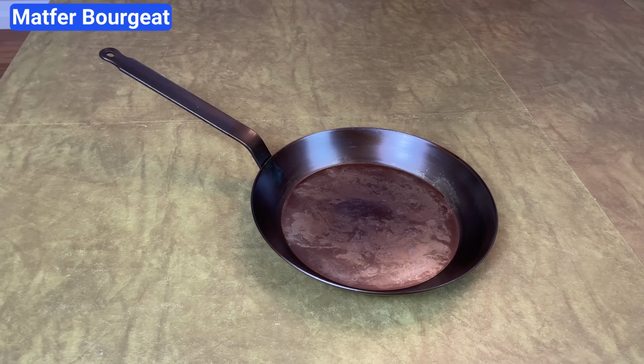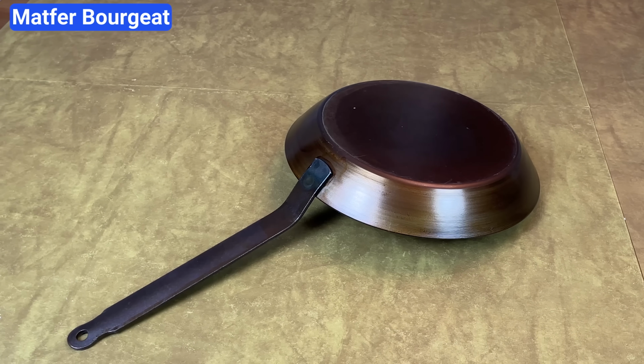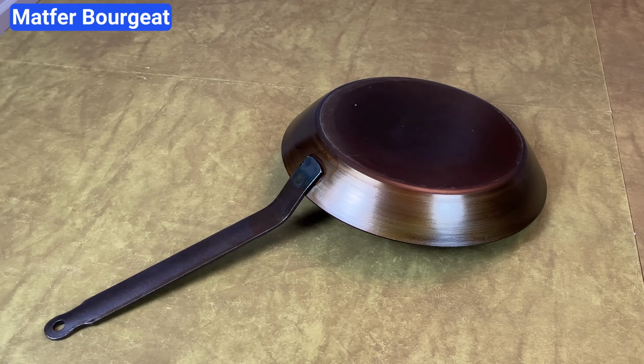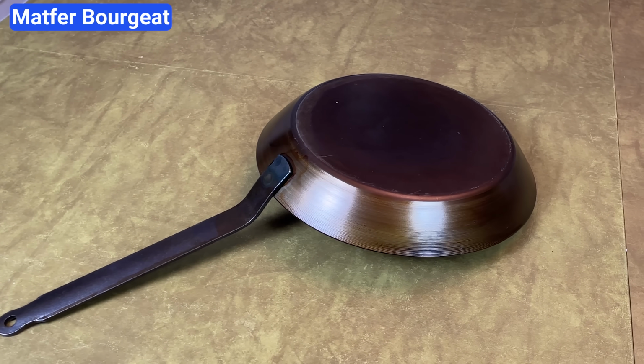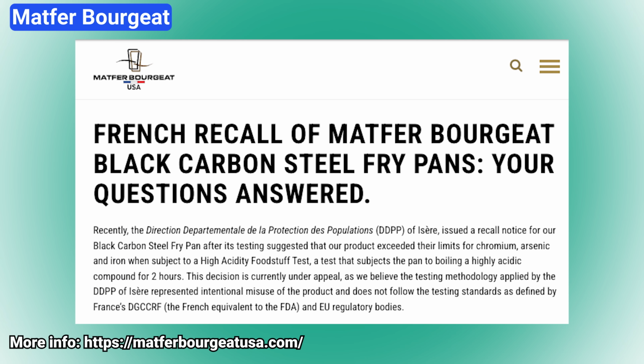But the most important thing you need to know about this pan is that although it's still available in the US, it's been recalled in France. This pan passed France's national safety standards, but regional regulators found that the pan released excessive levels of arsenic, chromium, and iron when cooked in a highly acidic solution for 2 hours. This goes against the pan's usage instructions, which warn you to avoid acidic foods.